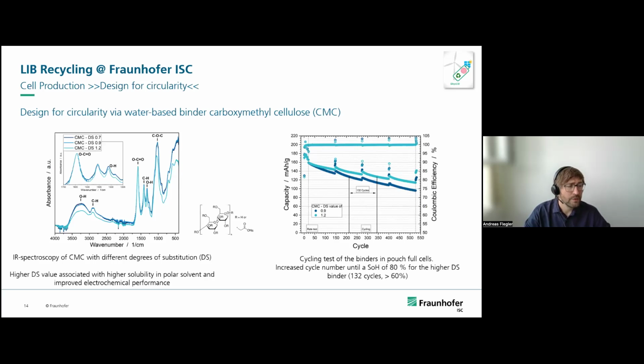So here we looked at the different CMC species. We looked at different degrees of substitution of the carboxy groups. And we see that a higher degree of substitution gives better solubility in the polar solvent. So we have a better distribution in the electrode and get better electrochemical performances.